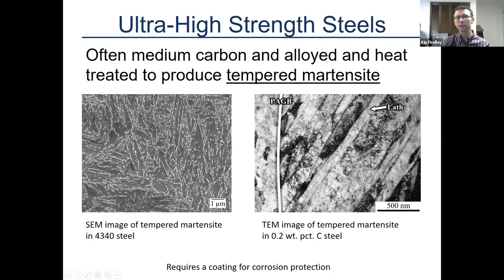So in landing gear, we typically use ultra high strength steels. And I'm not going to go into details of these, but we use a microstructure called tempered martensite. Again, look at the scale bar here. This is a really fine microstructure where things are designed in at the submicron level to give those materials high strength, high toughness, and even good fatigue resistance. And here's an even higher resolution image showing it's composed of things that we know are there that give the material these properties.